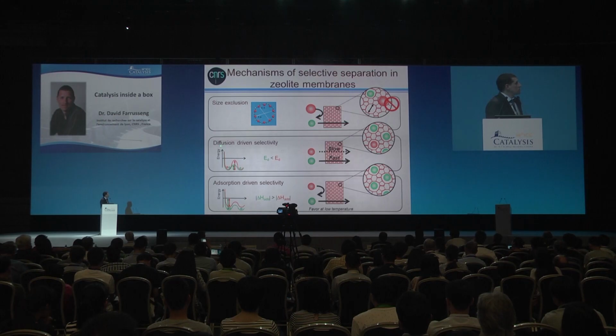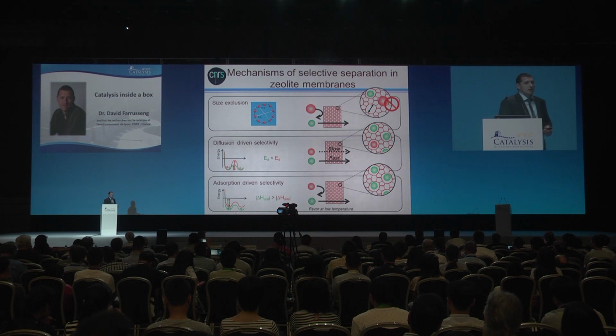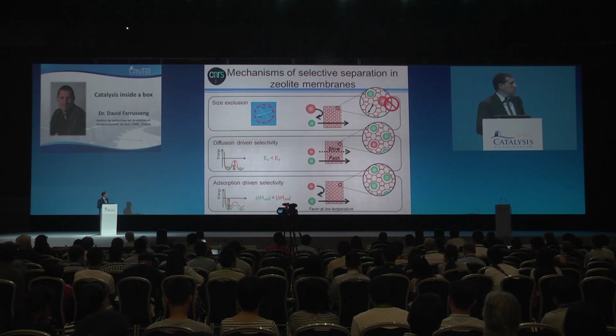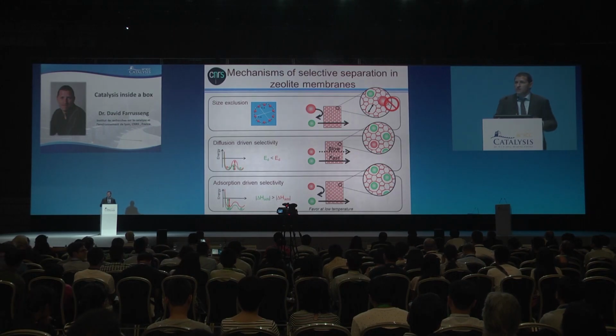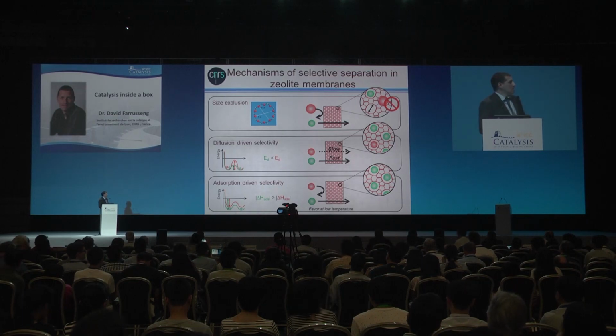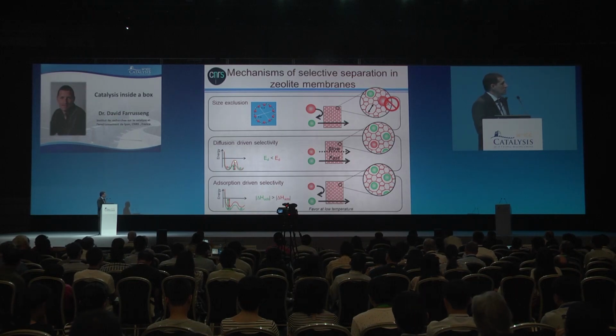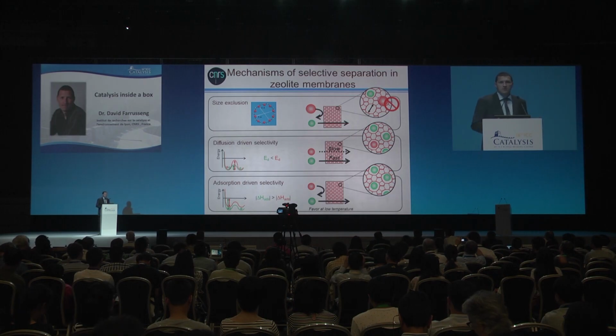The second is called diffusion-driven selectivity. Here, both substrates have sizes which are smaller than the pore window, so they are allowed to diffuse in the zeolite membrane, but one is a bit bulkier than the other. That would be, for example, the case of normal alkane and isoalkane. And because of that, one will have a much higher diffusion energy, and so will diffuse more slowly through the zeolite. I'm going to show you a way we can use that for enhancing the selectivity.